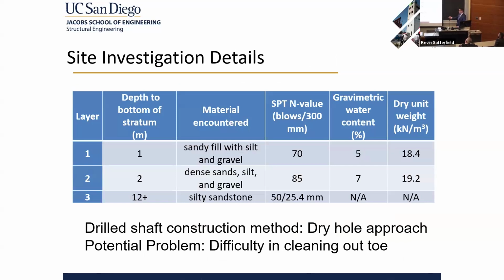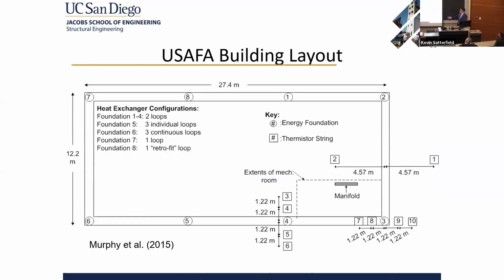We used a dry hole approach for the drill shaft construction. I found out after we installed them that these were installed by a water well installer instead of a drilled shaft installer. So the water well installers just want to go deeper than their required depth. So this driller drilled past our 15-meter limit and left the loose material at the toe of the pile. So basically he drilled down and then there was loose sand at the toe of the pile. In the normal dry hole approach, you're going to make sure that you have a nice flat material at the base. We didn't need this for the capacity of the foundation, but it added some complexity when we looked at the results later on. So here's the layout.